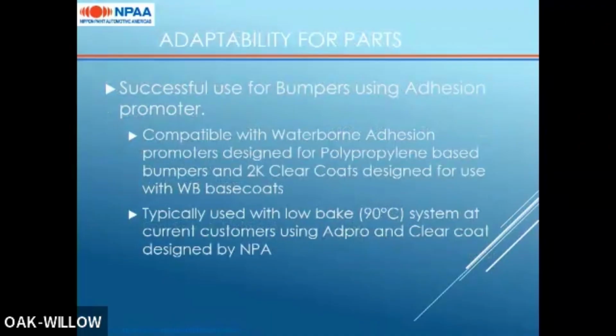Additionally, this technology is successfully used for bumpers using adhesion promoter. It's compatible with water-borne adhesion promoters that are designed for polypropylene-based bumpers, and 2K clear coats designed for use with water-borne basecoats. Currently, it's typically used with a low bake system of about 90 degrees Celsius for the clear coat at current customers using AdPro and clear coat designed by us.